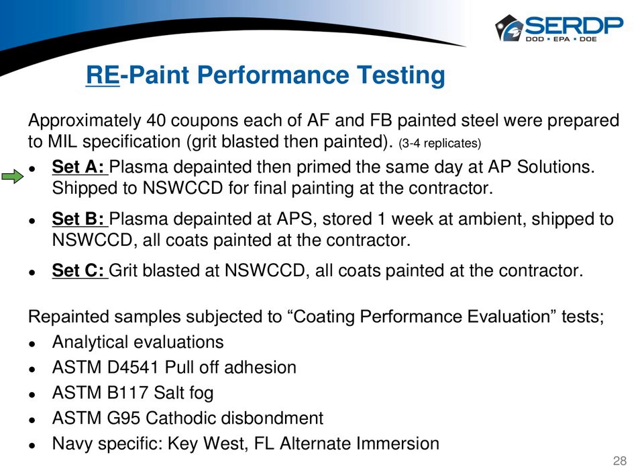This work was, we were interested in the stability of that oxide surface over time. So we produced two different types of samples. The first sample, once they were plasma depainted, they were primed same day. And the mil spec on grit blasting is you have to repaint within 4 hours, otherwise the surface has to be re-inspected and recertified. And the reason for that in a grit blasting environment in the marine is a lot of salts and water can alter that surface in 4 hours before it's repainted. So we let those samples sit. We did another set where they were stripped and then they're stored at least a week.